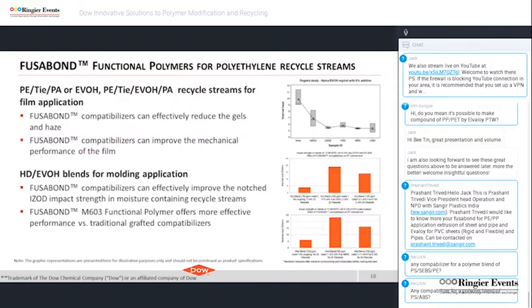This slide shows example of using Fusabond functional polymers for polyethylene recycled stream. Multi-layer films are common in packaging application and usually consist of two or more polymers such as PE PA EVOH and PE EVOH PA. And most of these films are co-extrusion film. Fusabond compatibilizer can effectively reduce the gel and haze and also improve the mechanical performance such as tear and tensile of the film. Hence, Fusabond enables the multi-layer films to be used back in film application.